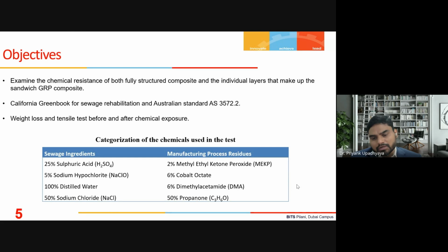And once the whole test is complete, before the testing starts, we do one tensile test to see what is the strength of the composite. And after the whole chemical exposure testing is completed, we do another tensile test to see the degradation that this chemical exposure is causing. So the chemicals that we have selected for this study can be categorized into 2 categories. One is coming from the sewage liquid that is present in the system. And there are 4 chemicals or liquids that we use for this testing. First one is sulfuric acid, second one is sodium hypochlorite, third one is sodium chloride, and the last one is distilled water, which is present in the sewage in any way because of over usage.